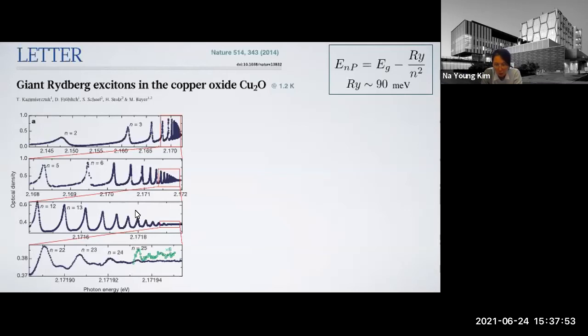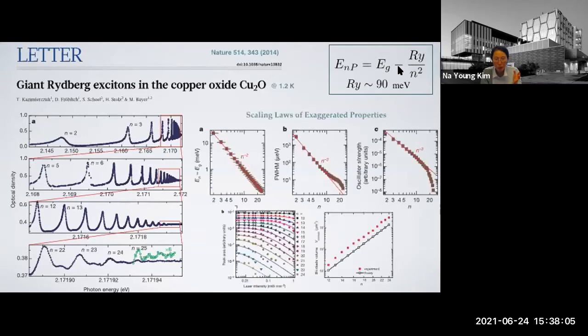And the formula is a little bit different from the hydrogen case, because in the semiconductor we have to consider the band gap energy. Right? From the band gap energy, this corresponds to the binding energy. And this, the authors show, is the scaling laws of the exaggerated properties of the cuprous oxide for the energy state or the binding energy as a function of n, or the spectral line width or the oscillator strength.